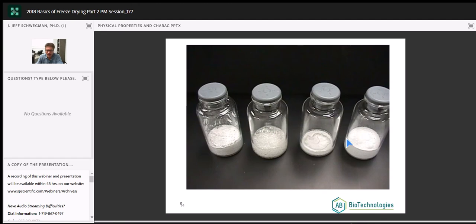This one actually looks pretty good. This one's collapsed in on itself. Basically, what happened here is that there was still a little bit of ice left over before we ramped to secondary drying, so primary drying was not complete. Well, what happens as we ramp to secondary drying, if there's still ice, once the product temperature exceeds 0 degrees Celsius, that ice is going to melt, and it's going to take down some of the material that's dried above it, okay? So collapsing of the center.